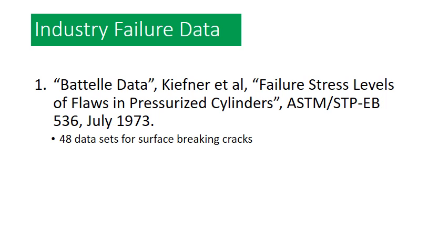Unfortunately, the data sets are not complete. There are some data sets that are missing their toughness information, which is quite important to this. What I've done here is I've decided to default to a Charpy toughness of 34 joules, full size, which is the equivalent to 25 foot-pounds. And 25 foot-pounds toughness is provided as a pretty reasonable guideline for the fracture toughness of pipeline steels. And that was actually recommended in a paper by Kiefner in 2004, a paper that was written for PHMSA. So I'm going to use that. It doesn't seem to affect the statistics too much, so I hope that you're okay with that assumption.